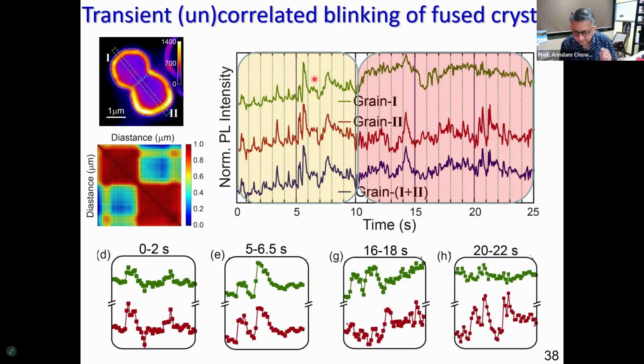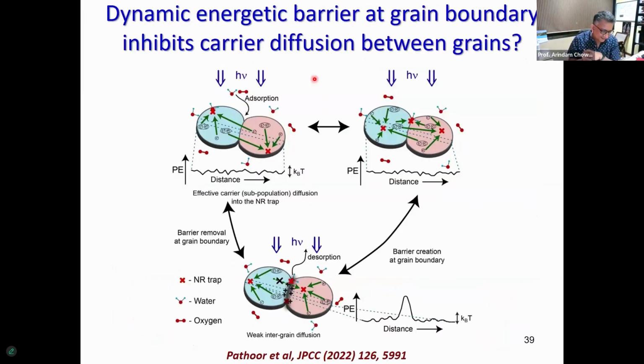And this is something that really perplexed us. After a lot of thinking and doing some experiments, we came up with a model. I'm cutting the long story short here. This is what we believe is happening, with some evidence: imagine you generate some of these quenchers or these charged species at the interface of these fused grains, at the grain boundaries. Then otherwise the carriers were free to move from one grain to another. But once you form some sort of a barrier in between these two grains, these two segments become electronically disconnected in some way. And that essentially makes the blinking of the grains uncorrelated. That is what we think is going on.